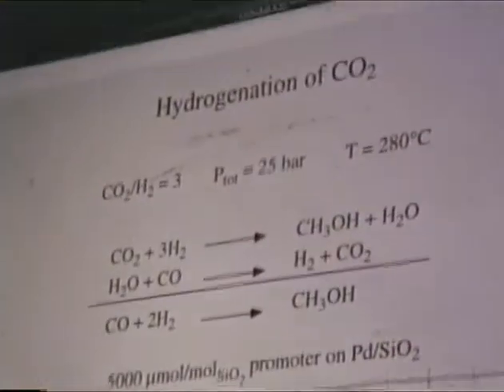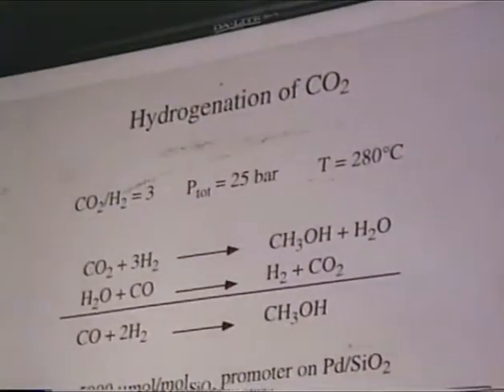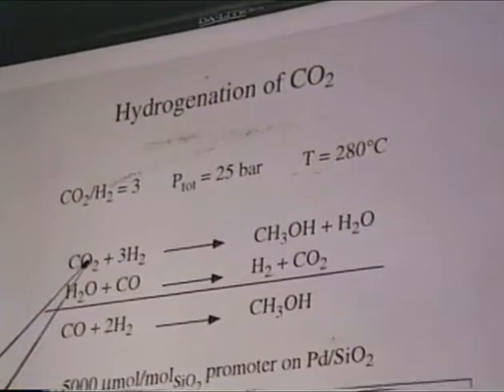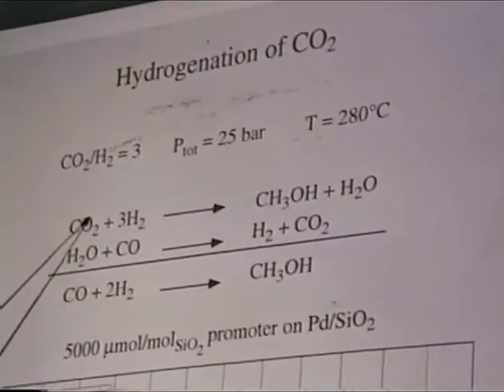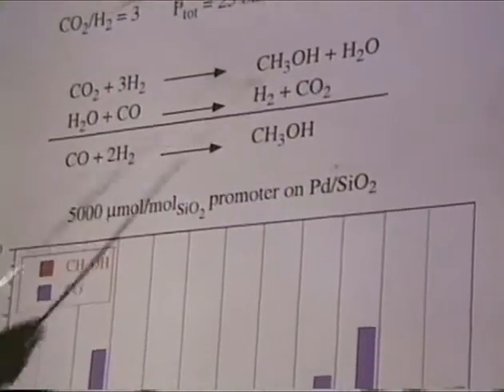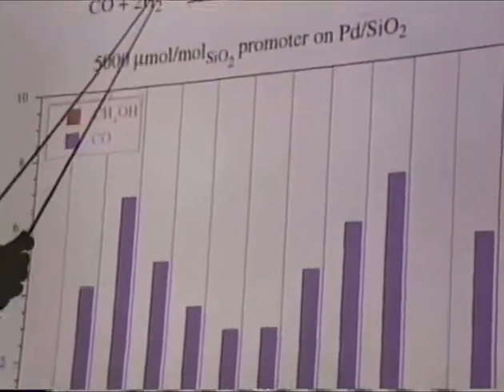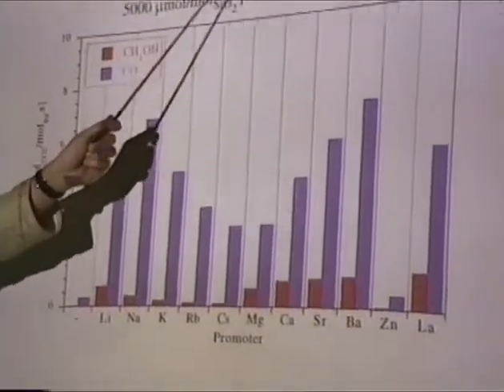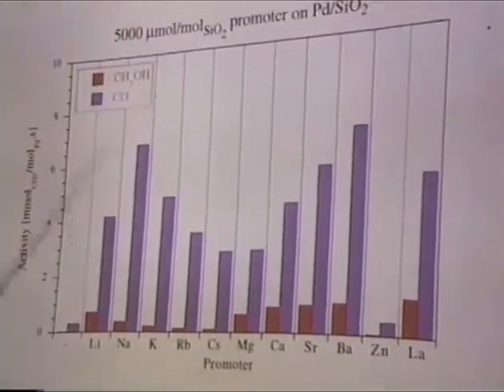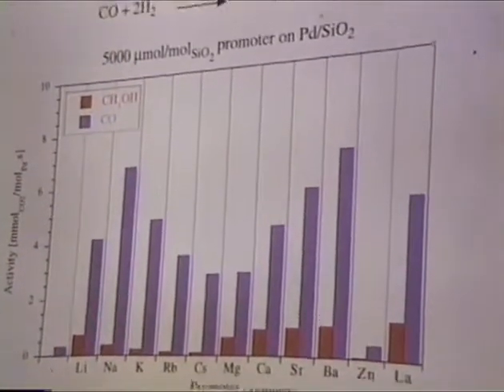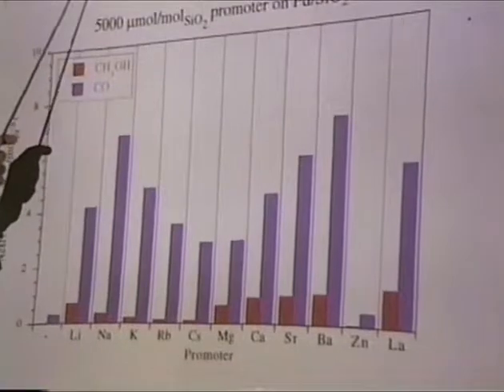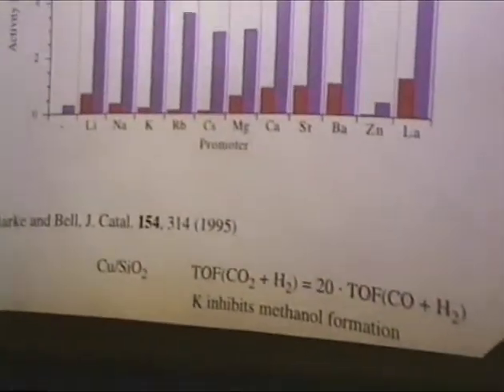And we all know that in the copper case, by now at least we know that the system doesn't go through the CO. It's not this reaction, but this is the Brutto reaction. You start with the CO2 actually, and it's the CO2 that goes to the methanol. However, the water with the CO gives you the water gas shift reaction, and you get the CO2, and the cycle is closed. So the Brutto reaction is still this, but it goes through the CO2.